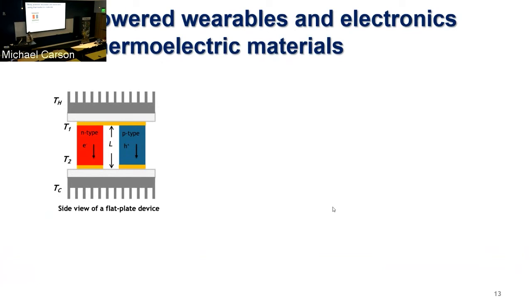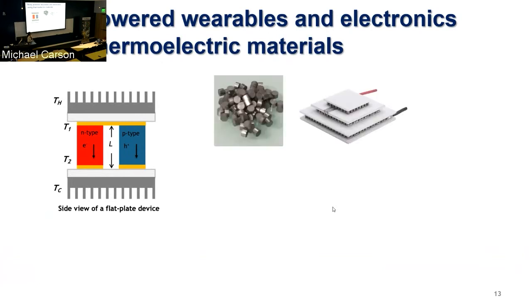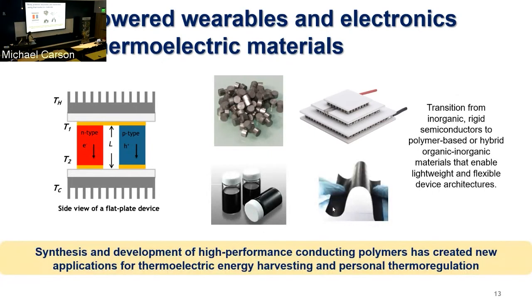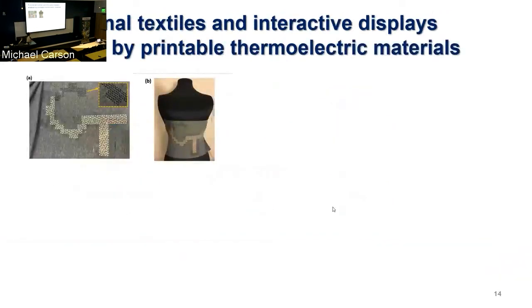Again, it requires P and N-type semiconductors similar to solar cells, but they have to have a much higher electrical conductivity in this case. The traditional thermoelectrics, you know, it's been around for decades, uses these inorganic rigid materials to form devices of this form factor. And what we've been focusing on at Georgia Tech really is how can we instead move towards organic thermoelectrics, which are solution processable and will allow us to do large scale manufacturing and also create very flexible and stretchable devices.